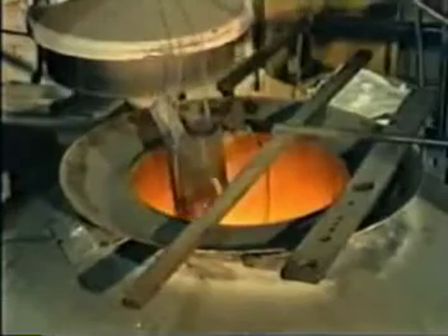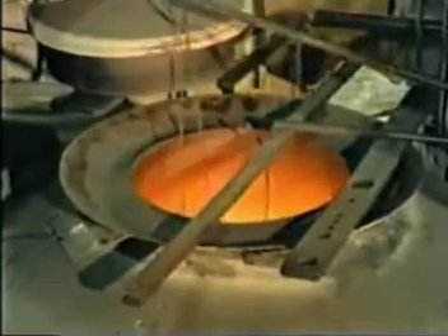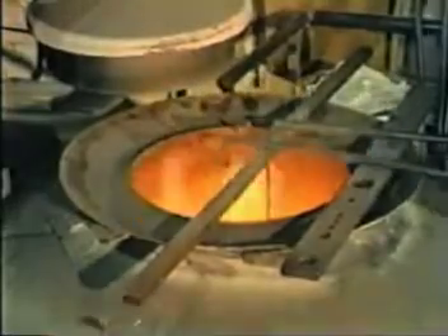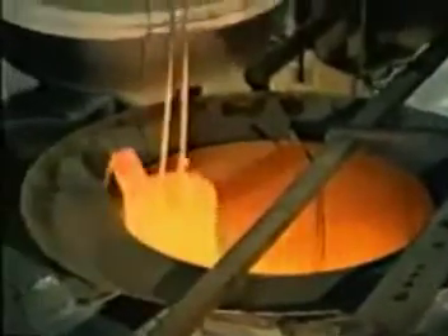The heating step is accomplished by loading the work to be hardened into a suitable environment that is already at the required hardening temperature, and then bringing the work to that temperature. This temperature is called the austenitizing or hardening temperature. Some of the more common types of equipment in use today for hardening are the open-fired furnace, the atmosphere-controlled integral quench furnace, as well as the molten salt bath and a fluidized bed furnace. The exact medium used for heating will vary depending upon the grade of material being processed, the geometry of the part, the end properties desired, and the experience of the heat treater.